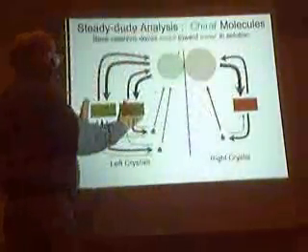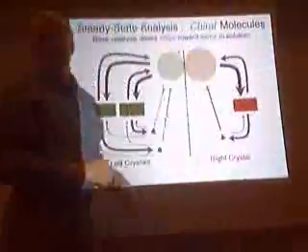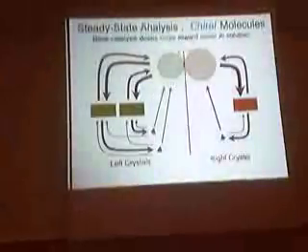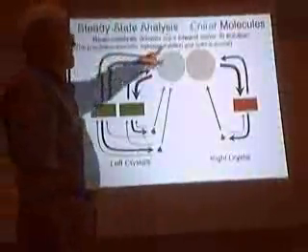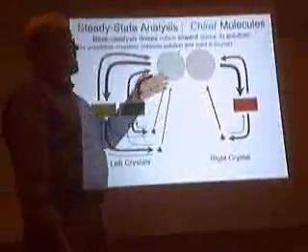This is major, and this is minor in the crystal. But in solution, this is major, and this is minor. Yeah, so that's happening now. And notice there's a population inversion between solution and solid. This is major in the solid. This is major in solution. And that's absolutely crucial. It's very, very important that that happen.